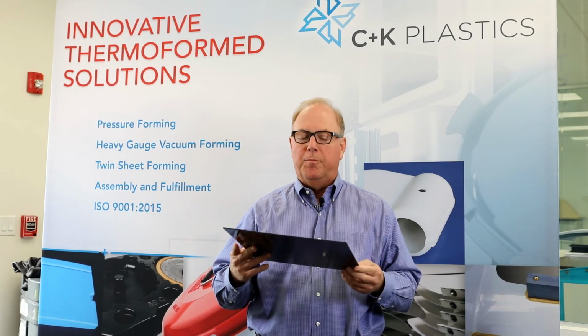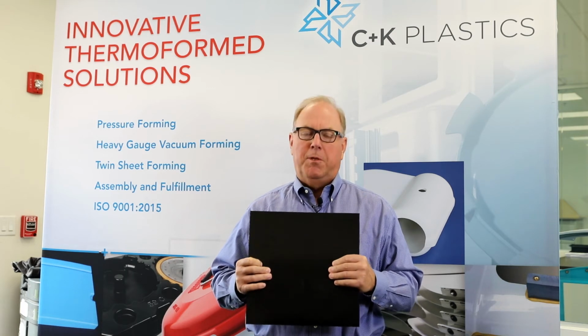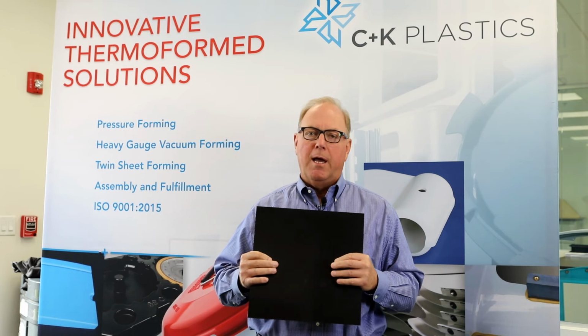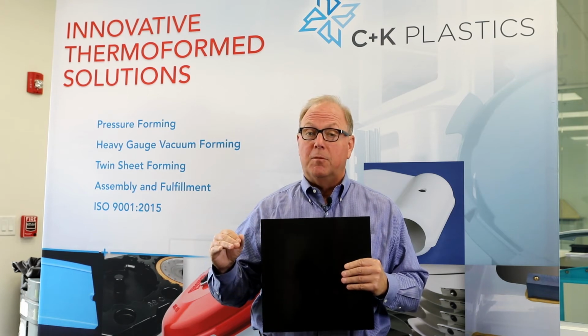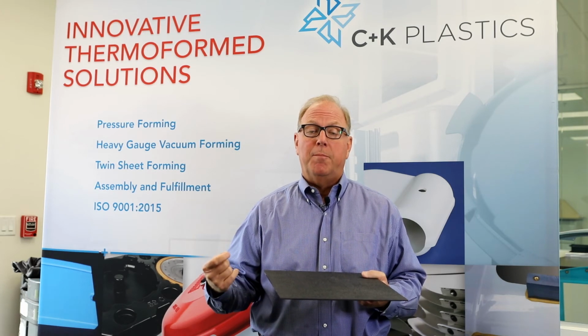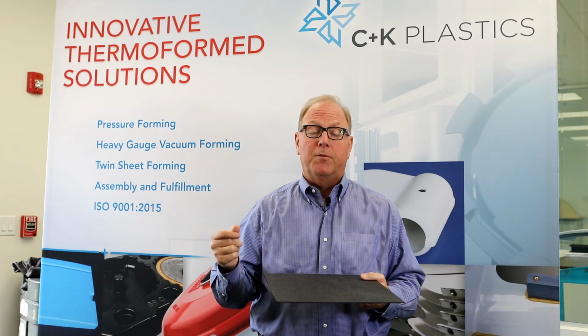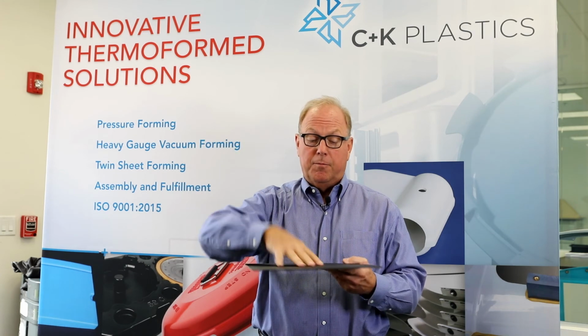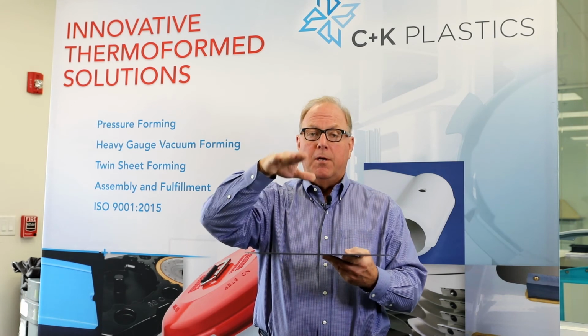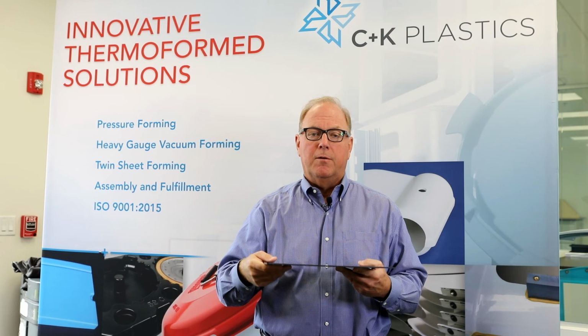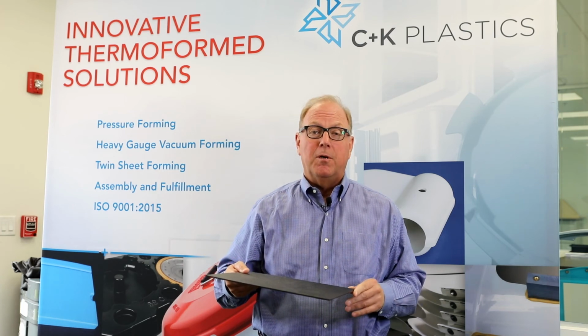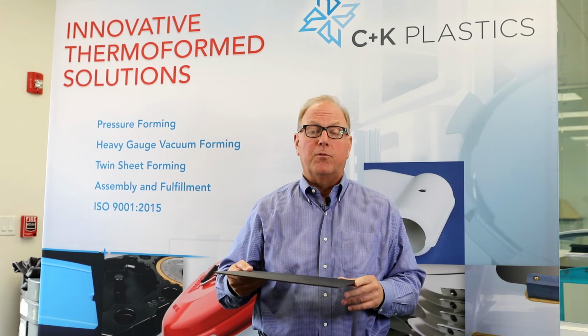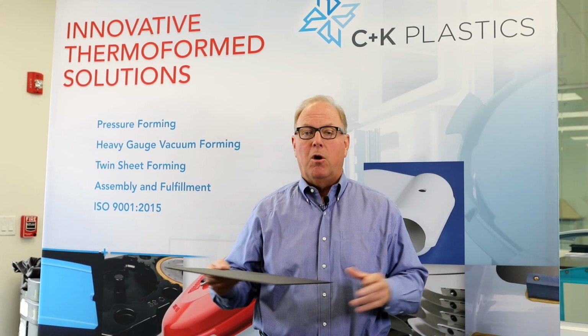You also have various different materials. A lot of times you'll go with semi-crystalline materials, all the olefins, the TPO, the polyethylene, the polypropylene, and you'll run sometimes utility material where the melt flow varies a little bit. So it's really important that you have other process controls within your system. You need to have pyrometers that measure the surface temperature of the material, and you can cycle off the temperature off the pyrometer. And a lot of times you use a sag eye. So whenever the sag of the bag at the glass transition point of the material hits that sag eye, it automatically rotates, and that's how we're able to run aluminized materials and, well, let's call it what it is, some wide spec polyolefin materials.